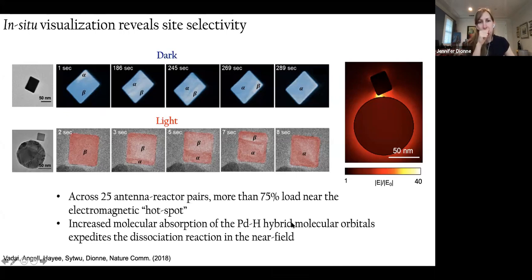And those that don't load near the tip do so mostly because the separation between the antenna and the reactor is too far. One thing we also notice is that upon illumination, you not only have nucleation of the new phase when you're closest to the antenna, namely the gold disk, but we also seem to see this edge nucleation. And I mentioned that we always saw corner nucleation followed by surface wetting, but upon illumination, in certain cases, we saw what seemed to be this edge as opposed to corner nucleation. We didn't know if that was mainly just expedited kinetics, like for example, maybe we didn't have the time resolution to capture the very rapid corner loading, or actually a new mechanism.